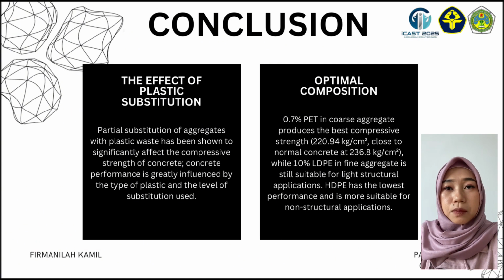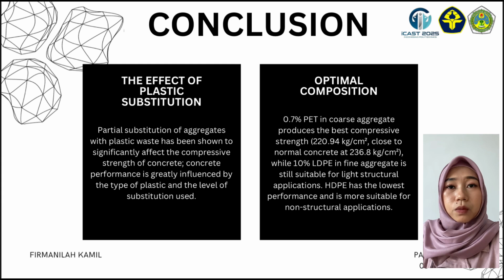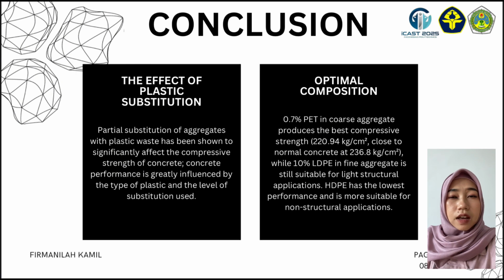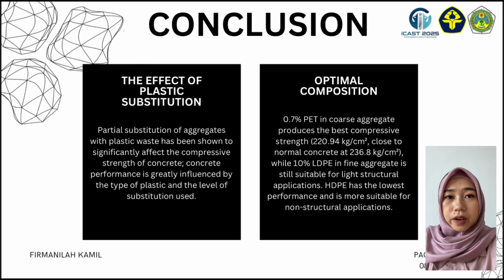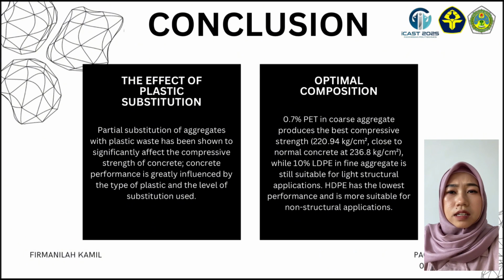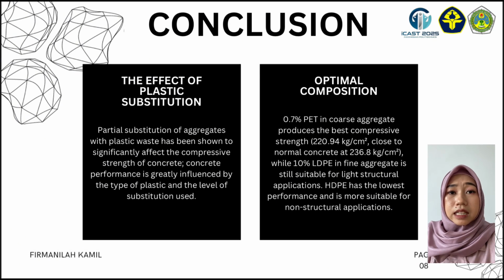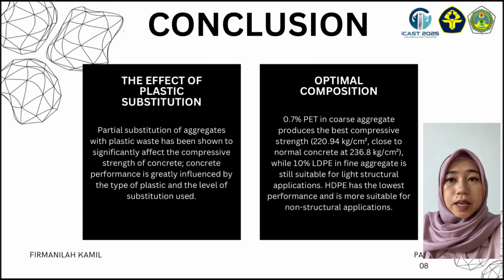2. Optimal composition. The most optimal result was obtained with 0.7% PET in coarse aggregate, achieving a compressive strength of 220.94 kg per square centimeter, which is very close to normal concrete at 236.8 kg per square centimeter. Meanwhile, 10% LDPE in fine aggregate remains suitable for light structural application. On the other hand, HDPE demonstrated the lowest performance, making it more appropriate for non-structural application.